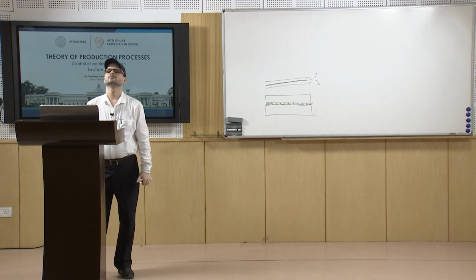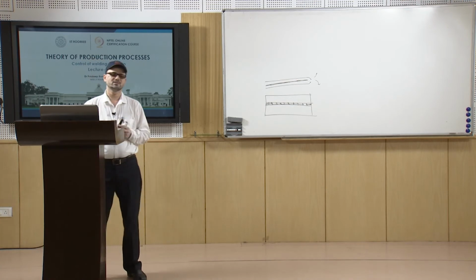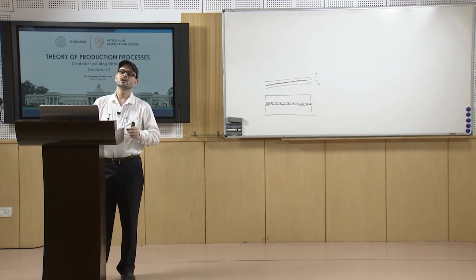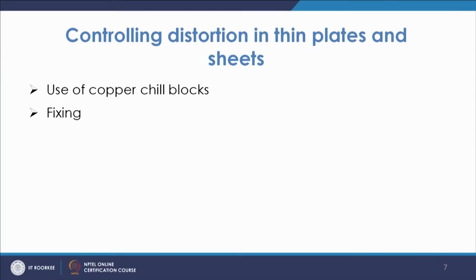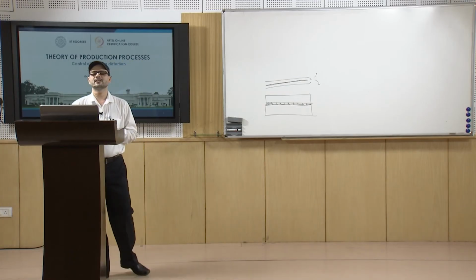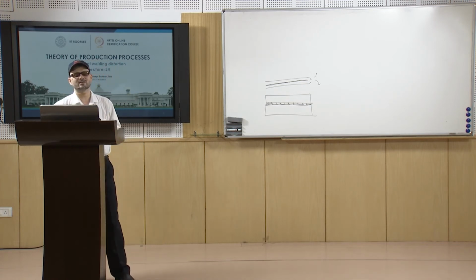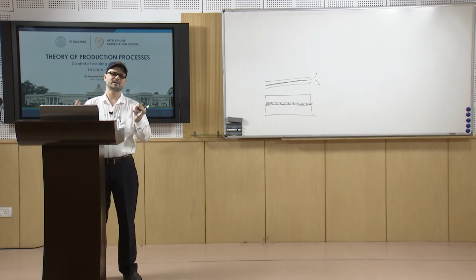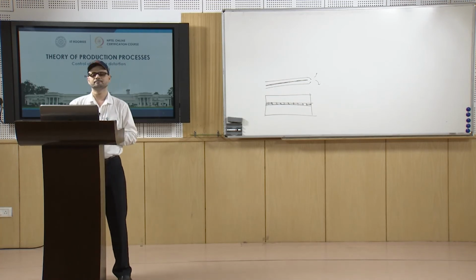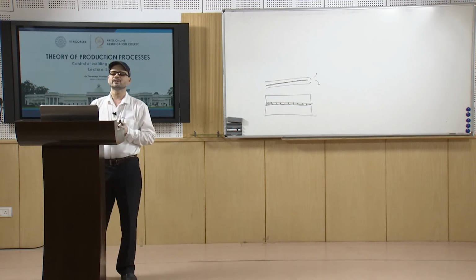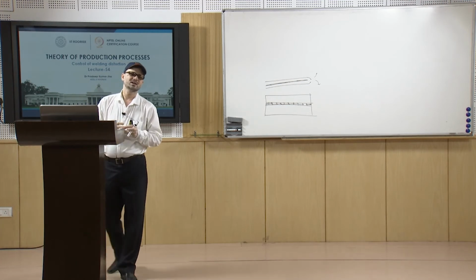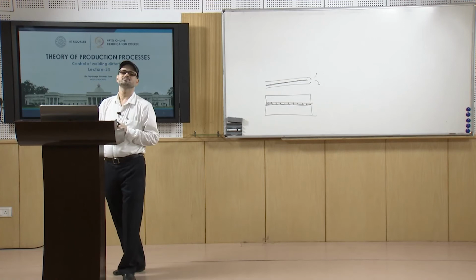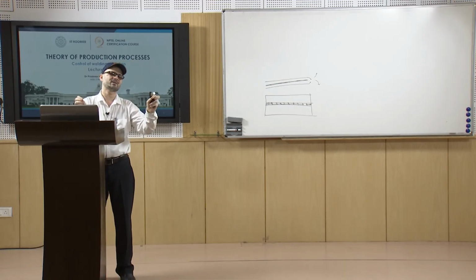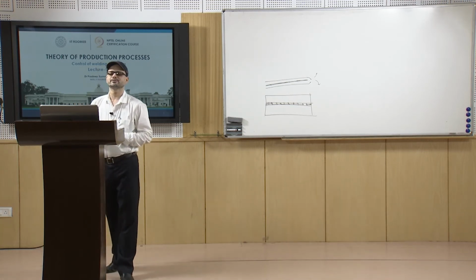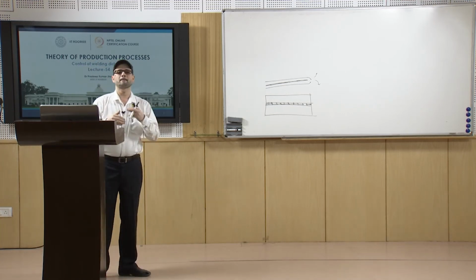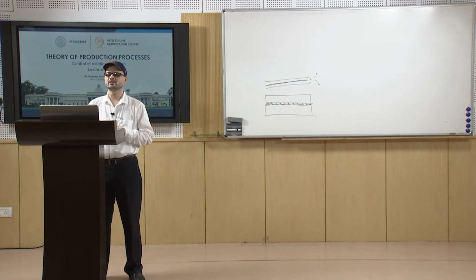Then you have other methods also for controlling, like many a times you use the counter or opposing setup. In this case, sometimes certain members, like the vertical members, you give a slight reverse bend, so they bend in a certain direction, like in a T joint. If you take the example of a T joint, there will be warpage due to the contraction of the weld. So, we give somewhat of a reverse bend so that the distortion is reduced. Once we have the reverse bend, then it will further bend in the opposite direction. So, ultimately you will get a flat type of structure. So, this is about the other methods for controlling the distortion.